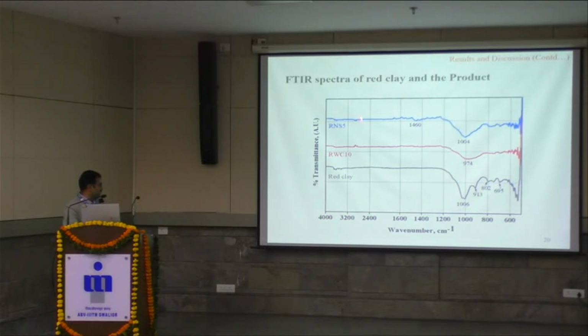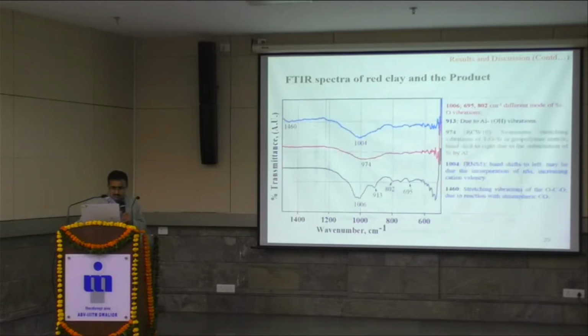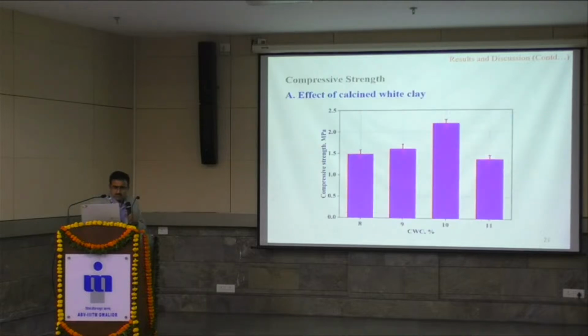When 5% silica was added, we have obtained this type of band which shifts from right to left. That can be seen here clearly. When calcined white clay was varied, an optimum compressive strength was obtained when 10% of calcined white clay was added.